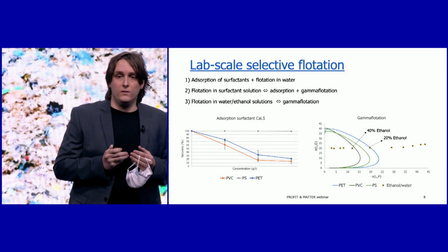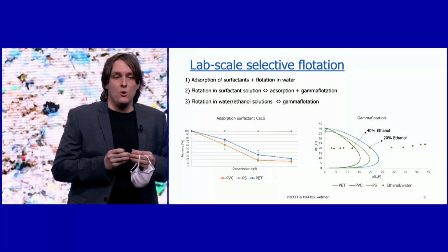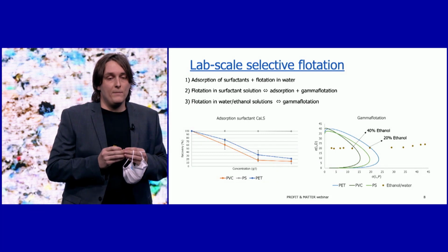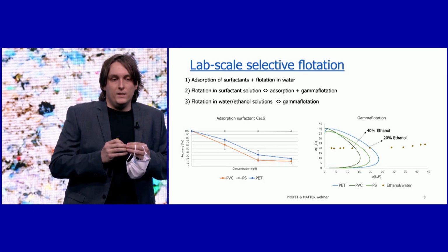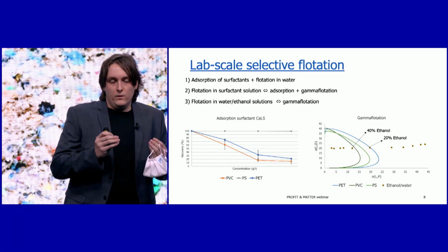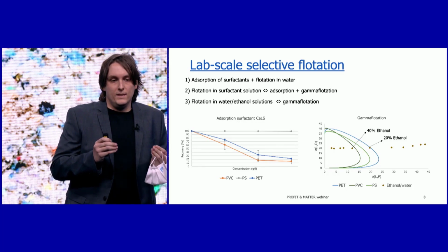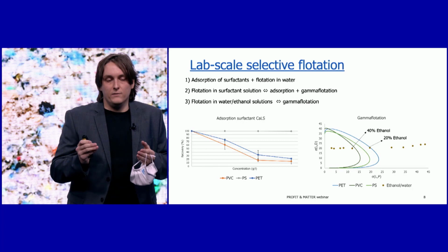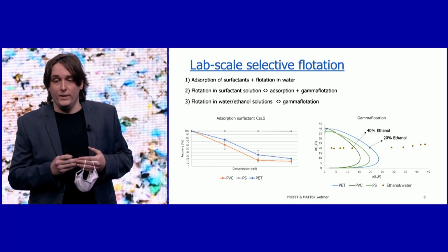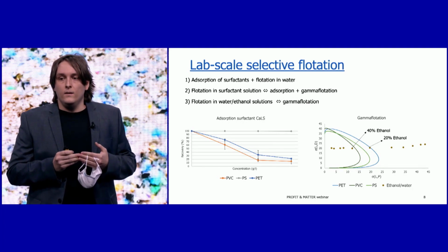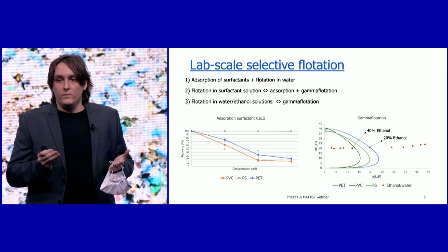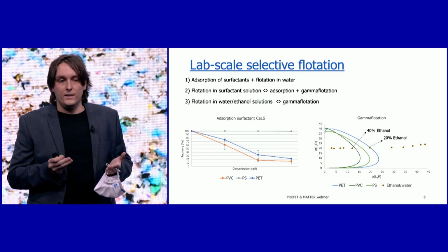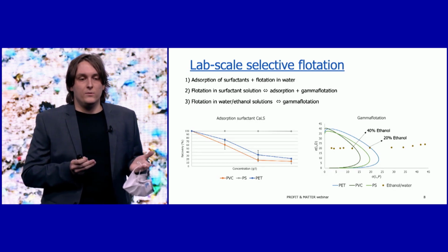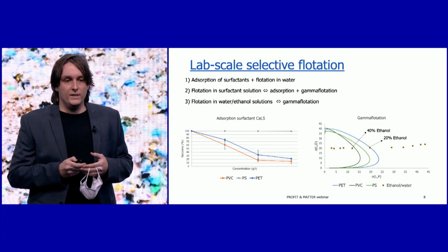The third series of experiments were focused on gamma flotation, a phenomenon in which only the flotation liquid is important in the selective flotation separation. From these measurements, it was clear that we could achieve a good separation between the different polymers.